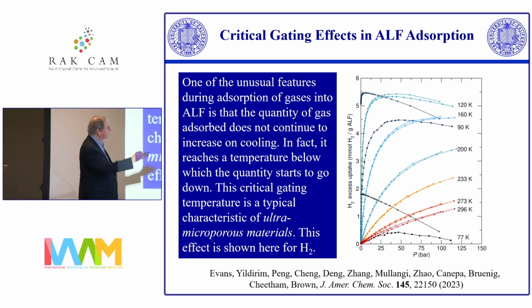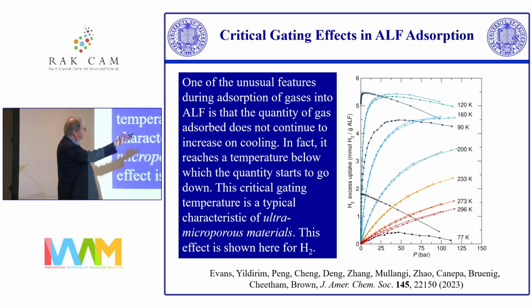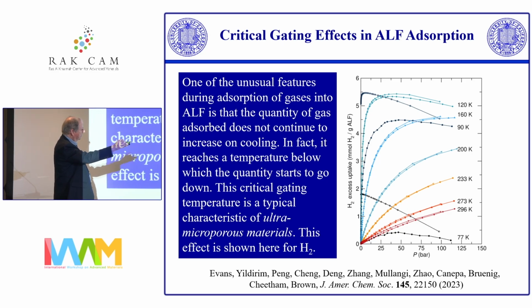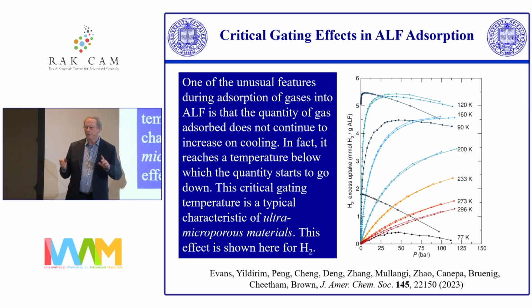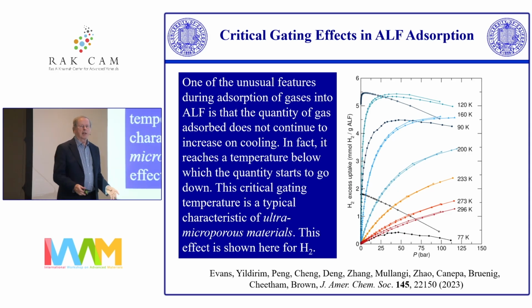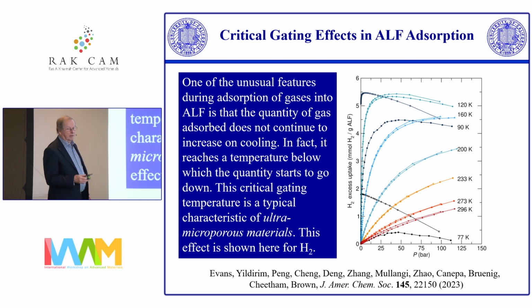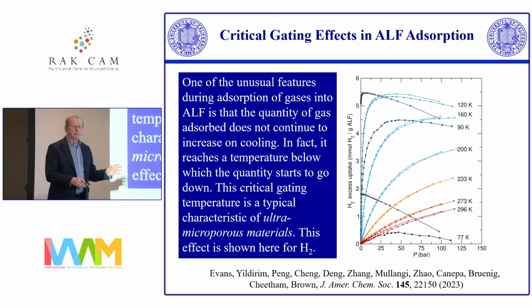I showed how the amount of hydrogen reduces if you go to higher temperatures, 120, 200 it goes down, and 230 and so on. I showed you that before. The funny thing is here, if you take the temperature down, you'd expect to get more and more gas going in if you went below 200. But what happens, if you're at 120, you're up here. Then if you're at 90 K, you're here.